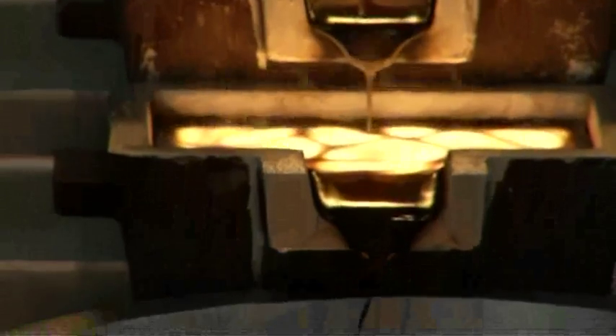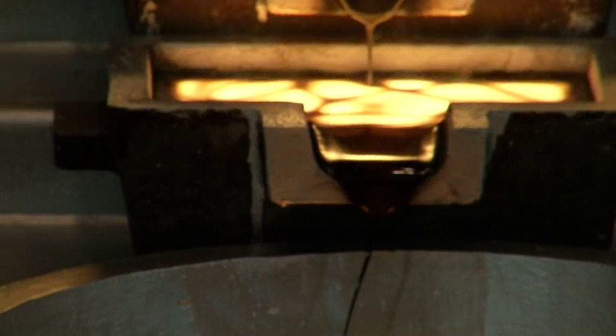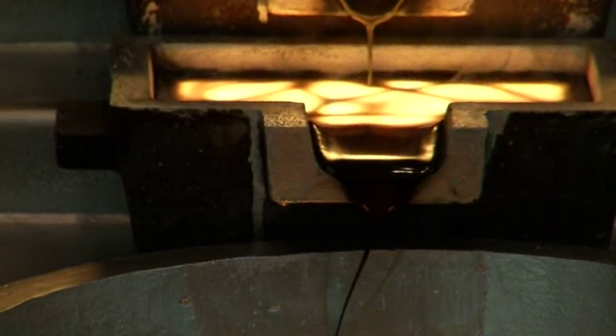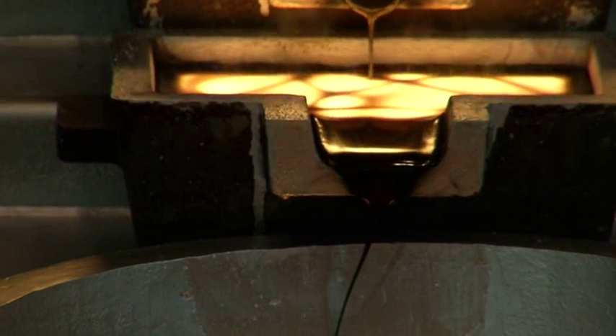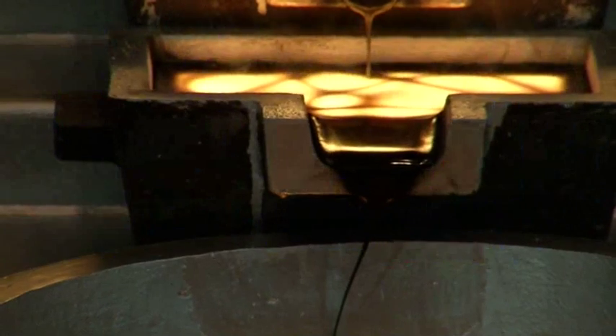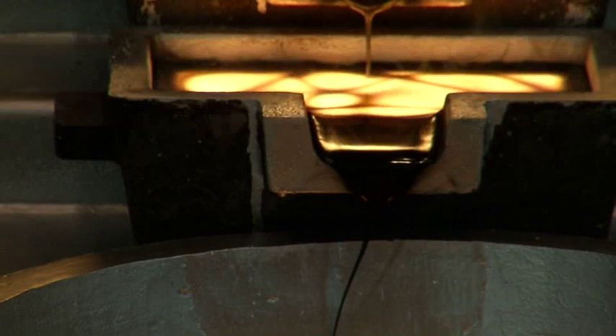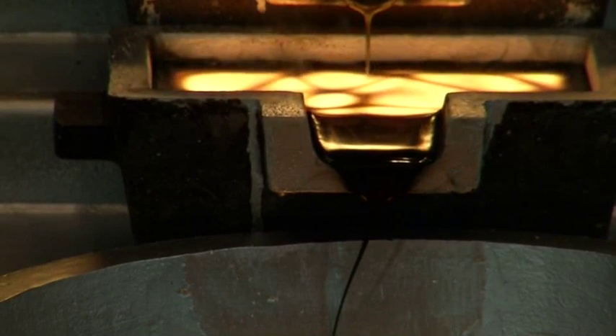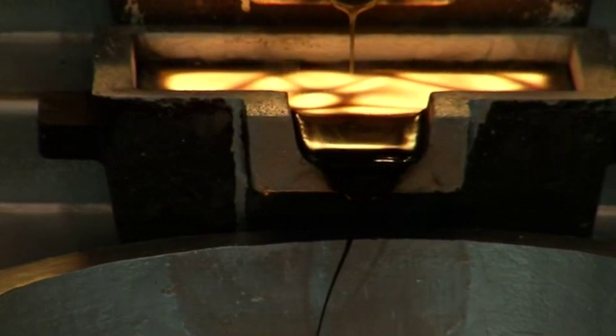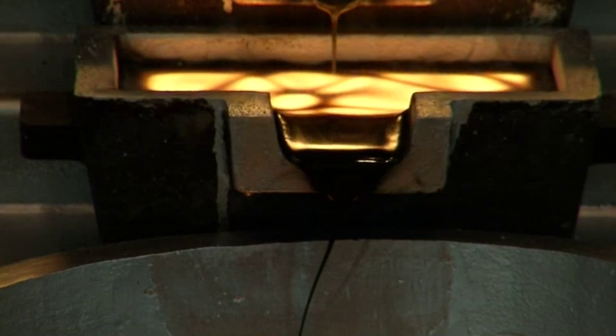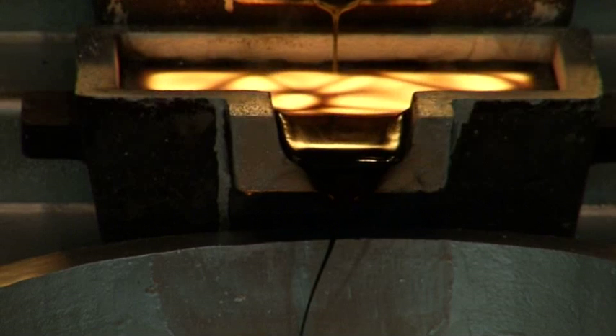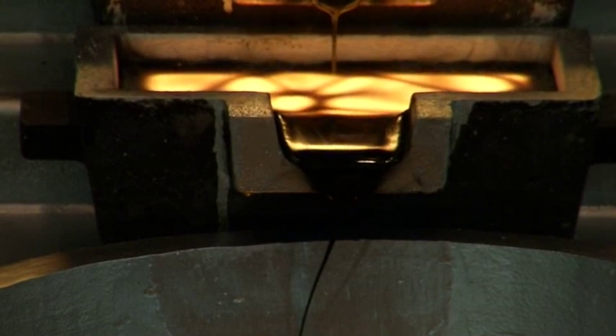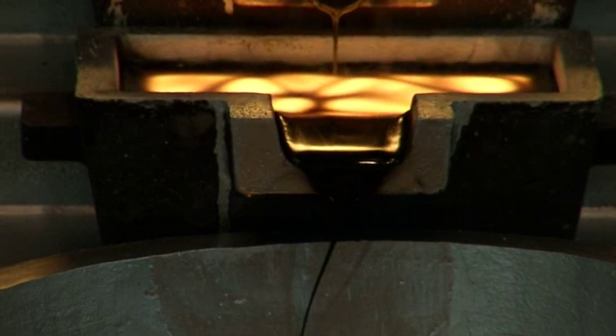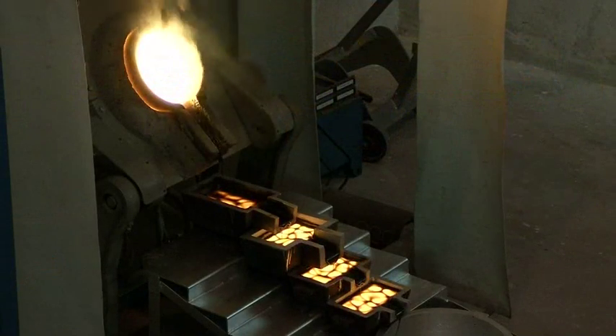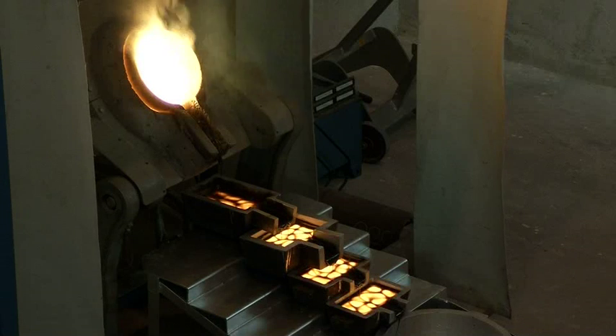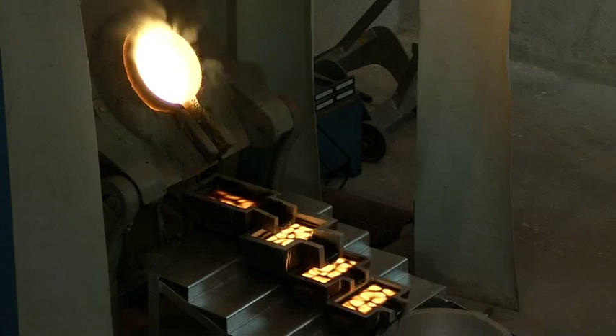As you can see, the shiny black material, that is slag. It's very obsidian glass-like, and he's busy just waiting for it to cool down to such an extent that he can mechanically maneuver those molds. Those molds are made from steel, by the way, and it doesn't melt. Because it's so thick, it manages to not go above the point at which the steel will melt with the slag. The pour happened at about 1,200 degrees Celsius. Gold melts at 1,063 degrees Celsius, but you need to have that hotter temperature in order to increase the fluidity and get the gold to sink down to the bottom. That was a very good pour.